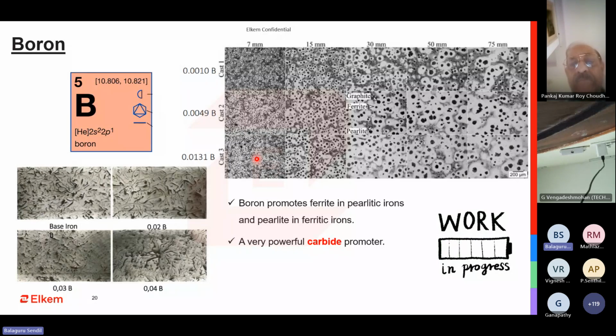So you have to ensure all other carbide promoting elements are kept under control. You operate with a very thin margin of eutectic temperatures, and you have to ensure you are casting within that particular range. If you have high boron, it spoils the shape of the graphite, and that is more visible when you have thick sections.